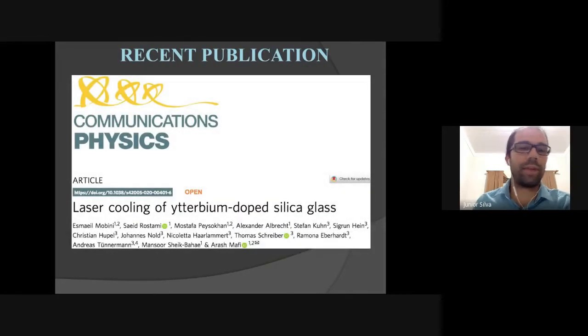Okay, that was a very nice publication recently, 6 or 9 months ago. People observed laser cooling of a ytterbium-doped silica glass. Never before had people observed cooling of an oxide glass. That was very nice, because in my opinion, I think this material cannot go to cryogenic temperatures, but can be a very interesting material for daily cooling applications, like our refrigerators, air conditioning. Maybe in the future we can have a laser and the silica glass producing our cooling systems.